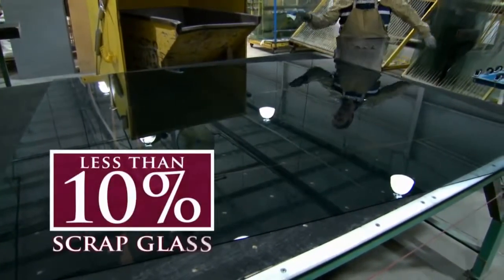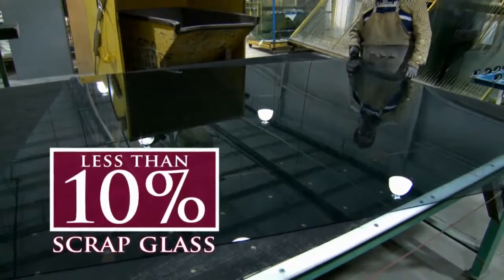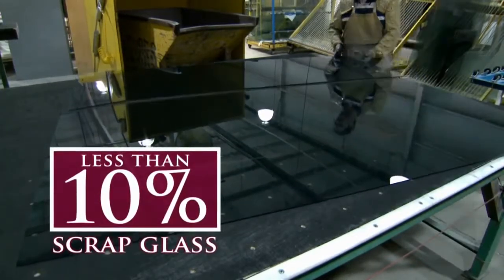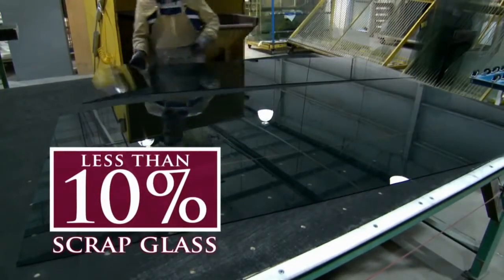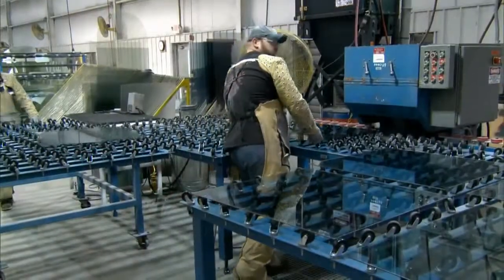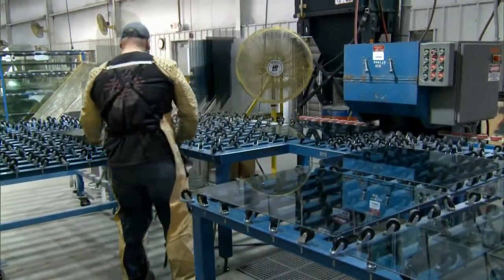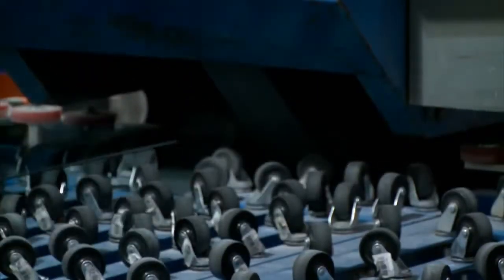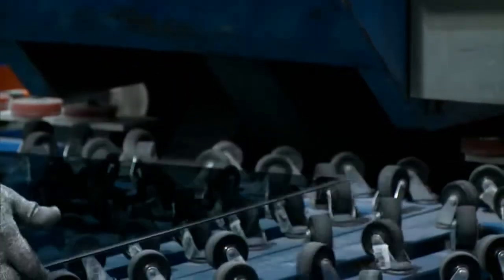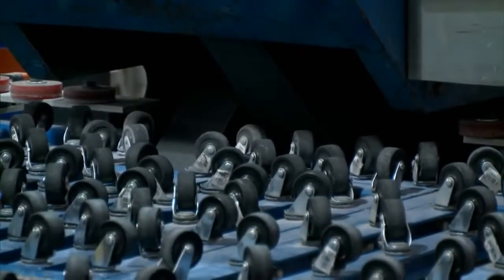We average less than 10% in scrap glass, but the small amount that does end up in the scrap bin is recycled. Before the glass is washed and tempered, or heated to add strength, we must first soften the edges on a grinding table. As a sheet of glass is tempered and is cooled, the heat rapidly leaves the pane at its edges. If the edges are not first softened, the glass will shatter during the tempering process.